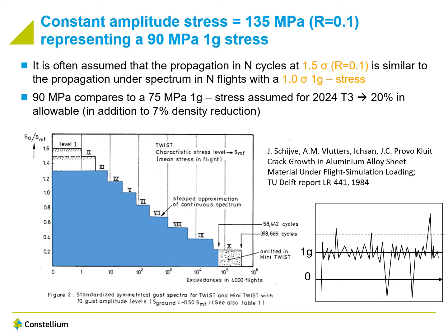So the 90 megapascal 1G stress is a relatively high stress, and that's what we want because we want an improvement versus a typical stress for a bulk material. For 2024 in the literature, we see 75 megapascal as a typical allowable fatigue stress or fatigue crack growth stress. It's rather on the high end of what is assumed for 2024 bulk material. So here we have a 20% improvement of allowable stress.